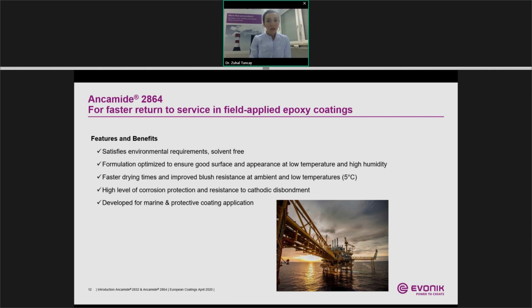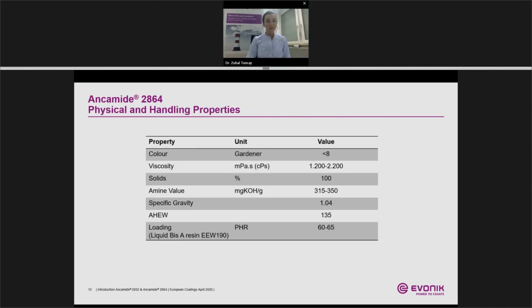Additionally, regarding the environment aspect, 2864 is solvent-free. And that product is developed for marine and protective coating applications. 2864 has a viscosity in the range of 1,200 to 2,200 millipascal second. It is 100% solid, and the preferred loading is 60 to 65 pHr for liquid epoxy resin.